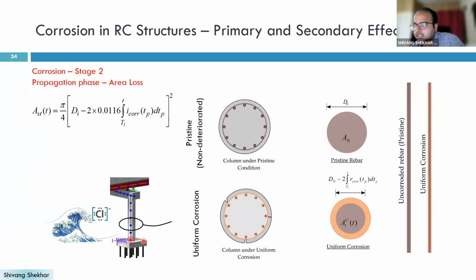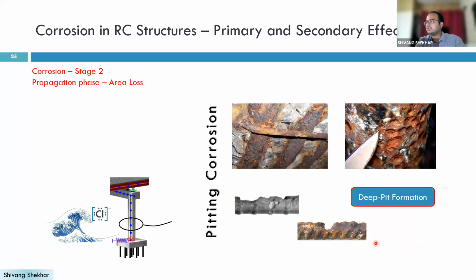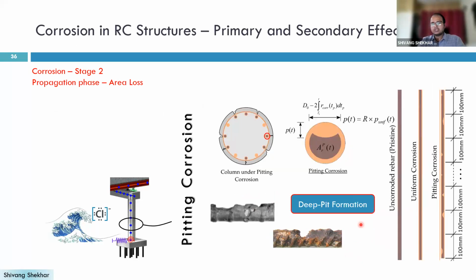Now, I was saying that chloride-induced corrosion not only leads to area loss, but this area loss is very non-uniform across the length of the rebar. Generally, when we model the cross-sectional area loss in the chloride environment for a beam or a column, we just take a uniform area loss. But experimental results from the past and real-world field scenarios also say that this corrosion is not uniform. Small pits form across the length of the rebar. We can see some of the figures showing these small pits along the length of the rebar.